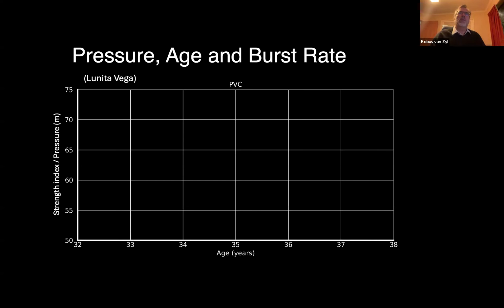And so that's what we did, was to say, okay, let's plot pipe age against pressure on this axis. And so 32 there is because the average PVC pipe in Auckland was 32 years old. And so we said from the data, if the pressure is 70 meters, we know there'll be 5 failures. Those dots represent 1, 2, 3, 4, 5 failures in that year for a typical DMA. But if the pressure is 55 meters, there'll only be 4 failures in that same year.